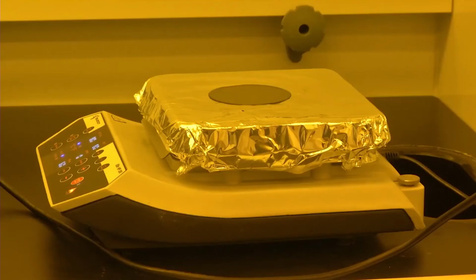So now we have spin coated and placed the wafer on a hot plate which was preheated at the dedicated temperature, which is 80 degrees for the first step. The question arises, why are we going for two different steps of heating? The reason is as follows. The first step ensures that a part of the solvent is evaporated and the substrate is nicely, firmly adhered to the spin coated polymer film.